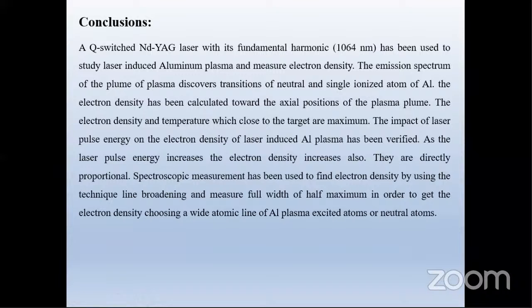Q-switched neodymium YAG laser with its fundamental harmonic 1064 nanometer has been used to study laser-induced aluminum plasma and measure electron density. The emission spectrum of the plume of a plasma discovers transitions of neutral and single ionized atoms of aluminum. The electron density has been calculated toward the axial position of the plasma plume. The electron density and temperature close to the target are maximum. The impact of laser pulse energy on the electron density of laser-induced aluminum plasma has been verified.